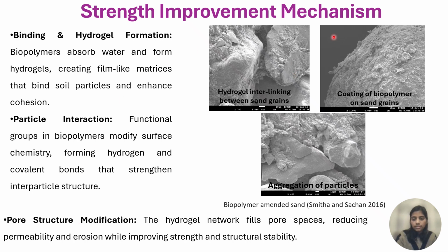The third one is pore structure modification. The hydrogel can fill the pore spaces, reducing the permeability and erosion while improving the strength and structural stability. And these are the SEM images showing agar biopolymer treated sandy soil. Here you can observe the hydrogel interlinking between sand grains and coating over the soil particles, and also aggregation and pore filling between the soil grains.